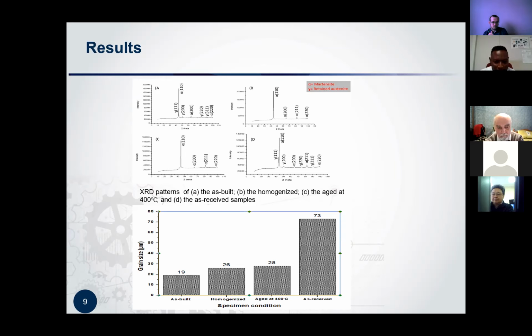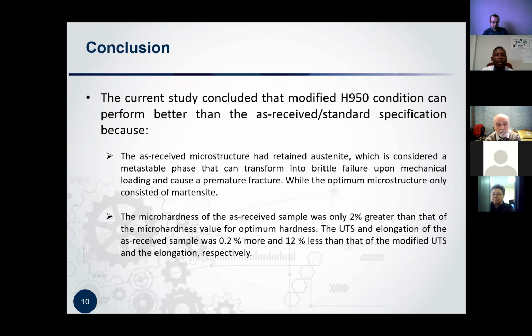So we further looked at the grain sizes. You can see, even in terms of grain sizes, for the as received, it was 73 microns. And then for the optimum one, it was about 28, which is a huge difference. And in terms of metallurgical perspective, grain growth is not really recommended. So I think this brings me to my conclusion.